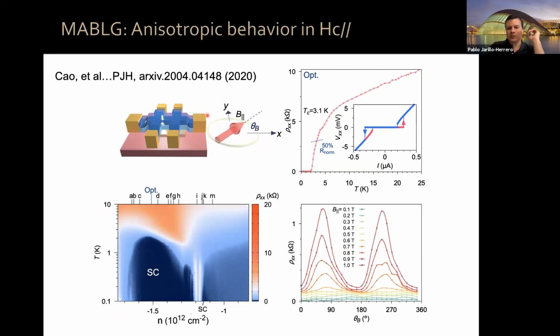And then what we can do now is measure the resistivity of the system as a function of in-plane magnetic field direction and in-plane magnetic field magnitude. So here you have your resistivity as a function of in-plane magnetic field direction at different magnitudes, and what you can see is there is this twofold behavior of the resistivity. Twofold again means an ellipse, because it has two maxima. Let me show you the ellipse. This is the resistivity as a function of magnetic field in the x direction and in the y direction. And as you can see, there is this ellipse. Here, blue means superconductivity, red means when it gets out of the superconducting state. And as you can see, the critical in-plane magnetic field has a different value in this direction and in this direction, hence this ellipse.